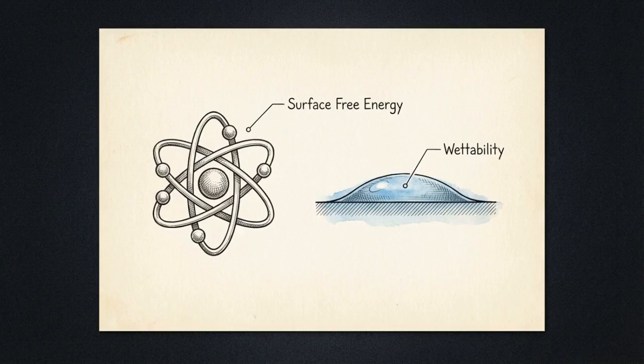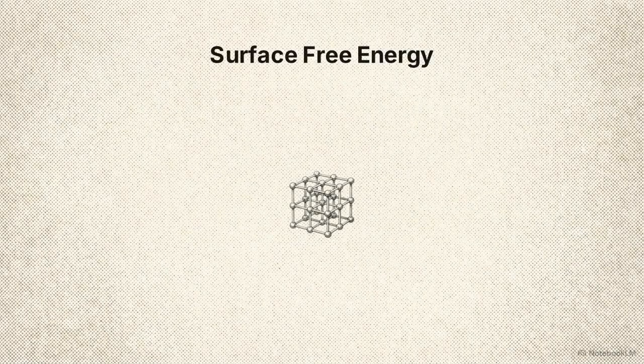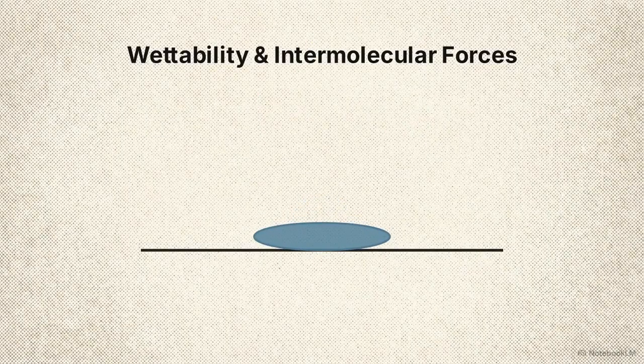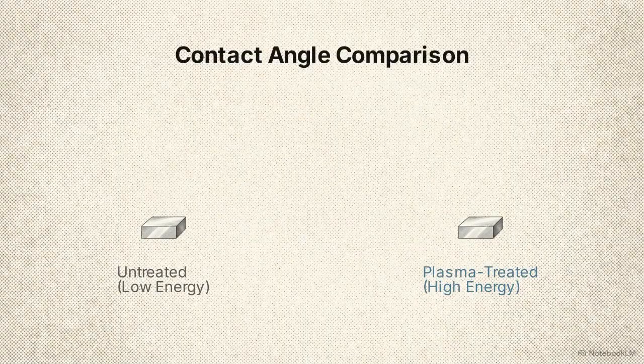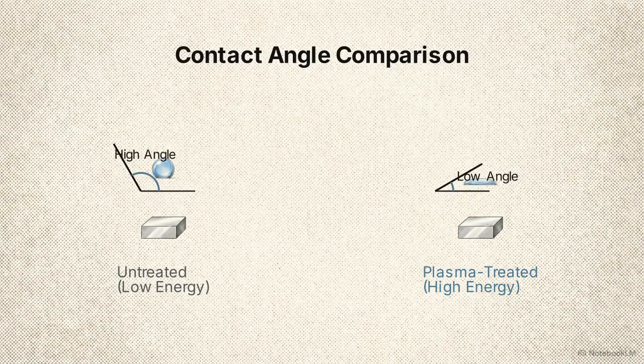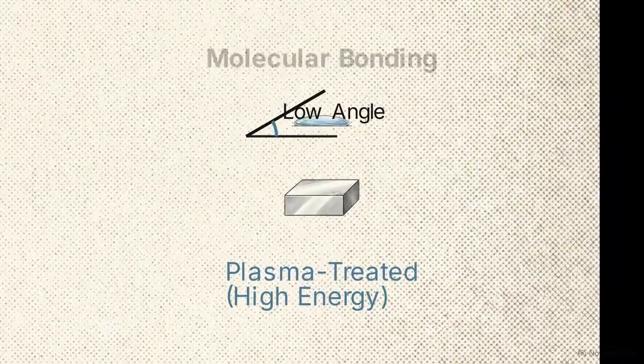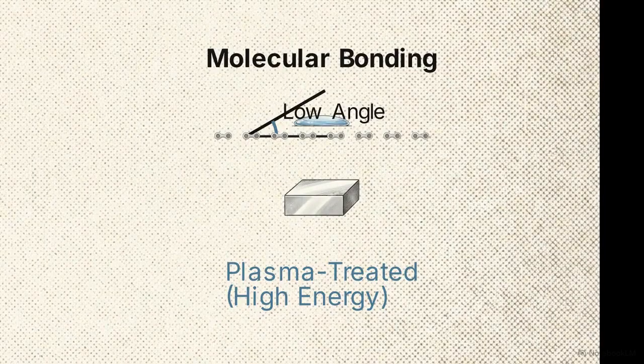This process increases two critical metrics: surface free energy and wettability. Surface free energy is the excess energy at the surface compared to its bulk, dictating how strongly it will bond with another substance. Wettability is the ability of a liquid to maintain contact with a solid surface, driven by intermolecular interactions. This contact angle measurement compares a water droplet on an untreated surface to one on a plasma-treated surface. The spherical droplet indicates low energy. The flattened droplet proves a massive increase in wettability, allowing molecular bonding without physical jaggedness.